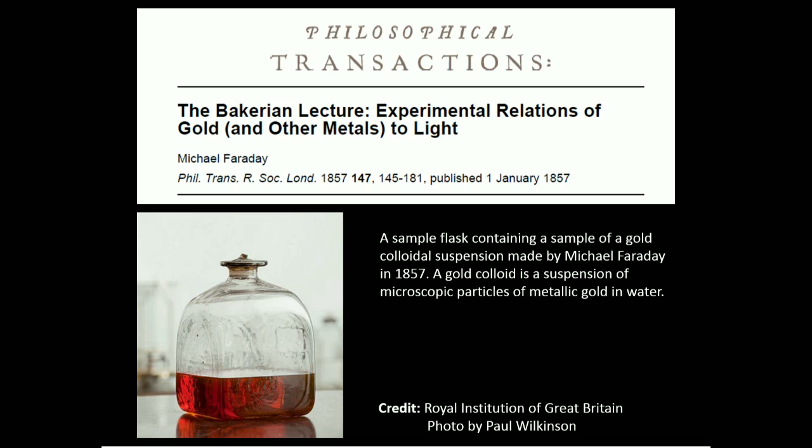It tells you the stability, and the beautiful red color here is derived from the way in which light interacts with very small gold nanoparticles, where it drives collective electron oscillations very efficiently at a surface plasmon resonance, which causes spectrally dependent absorption.